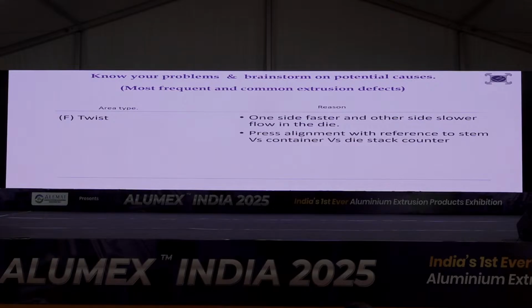But the biggest problem is if you have a constant drop at one side of the stem, it cannot give you a concentric force, concentric pressure to the die for exit. Just like what we see every morning, if we press a toothpaste tube from one side, the toothpaste doesn't come out concentrically. It comes out either this way or that way. So if that happens during extrusion, it becomes very difficult to control in the stretching. Many people say that we have a detwister in the stretching machine. It's a wrong thing. You just can't use the detwister in a stretching machine with your visual estimation.